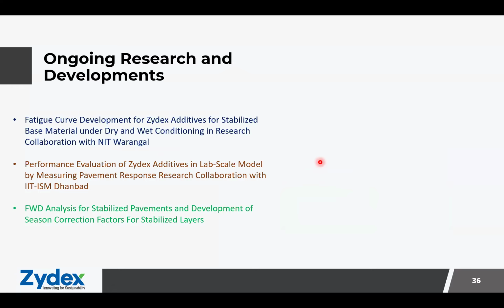Further, we are also working on the stabilization, and we are developing the methods. As I demonstrated, we are developing the fatigue curve for the Zydex additives under both dry and wet conditions, because wet condition is the most critical, and for that we need to design our pavement, because we have 90 to 100 days of monsoon season. This project we are doing with NIT Warangal.